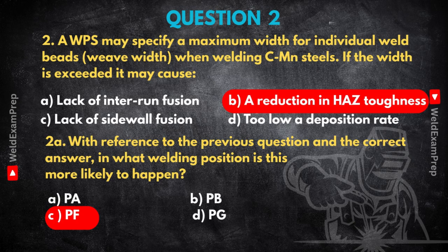But that necessary technique, that wider weave, inherently means putting more heat into a larger area with each pass. The heat input is higher, and it lingers longer in the HAZ compared to other positions. Right, because you're moving slower overall, maybe. Yeah, exactly. Slower vertical progression often goes hand in hand with managing that puddle uphill. So that combination, the wider weave needed for control, plus potentially slower travel, really increases the risk of overheating the HAZ and getting that grain coarsening, that reduction in toughness we talked about.